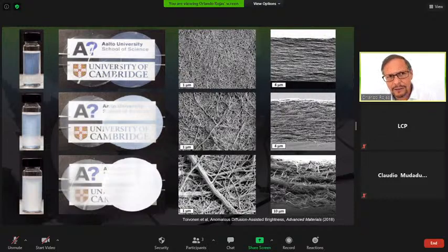But even here, the properties are even more interesting because we're in the nanoscale domain. And what we notice is the effect of something that we call super diffusion of light by using nanocellulose. So we go beyond paper. In this sense, we go beyond the traditional theories of light scattering with paper at this scale. And that's quite interesting because that means that we can fine tune paper coating and formulations to produce transparency or high opacity.